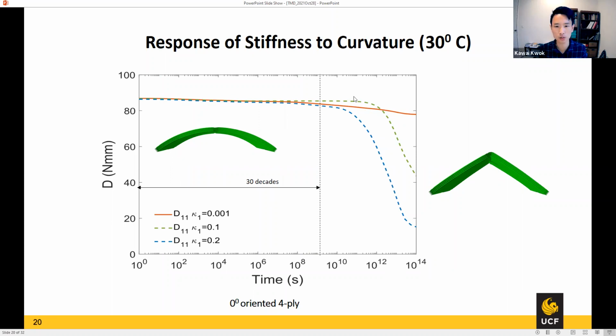So we subject that to a high curvature and a low curvature on this unit cell. Basically the red curve is what we're expecting normally, where you just keep relaxing over time and it keeps the shape of uniform bending indefinitely. However, what we observe is that if you increase that fixed curvature, all these simulations are at a fixed curvature, and we're looking at how the stiffness goes down. If you go to higher curvatures, you see that at some point in time there's a drastic drop in the stiffness. So we look at the deformed shape again for these two cases where we see this very sudden drop.